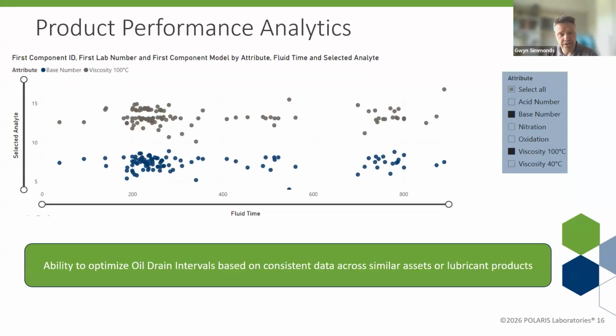And in terms of the current status, as Danny mentioned several times in his session, are we changing oil too early? Now, you can't really determine how good the lubricant is without sampling, without testing. But if you have accurate information on the sample, on the running time, it allows you to perform scatter plots and scattergrams to see, right, well, what is the condition of the oil over certain time periods? We change the oil at 500 hours. Why? Because that's what the OEM says. That's what the fluid manufacturer says. Well, if after 500 hours, all of the oil condition parameters are still at a satisfactory level, there's no significant contamination or wear, then really it does allow you to safely extend or optimize your drain intervals, which could become apparent in coming weeks and months across all of your lubricant products, purely based on the data that the laboratory provides.